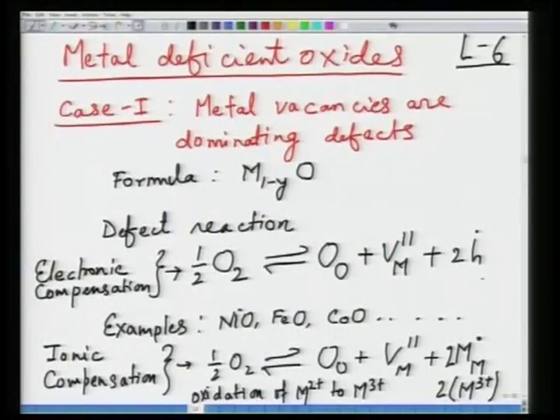Now, typically what you will find, these materials are susceptible to having extra holes. So metal vacancy is often complemented by creation of extra holes, giving rise to a p-type conduction behavior in these materials. Now we will take the second case. Second case is when you can have oxygen interstitial as dominating defect.